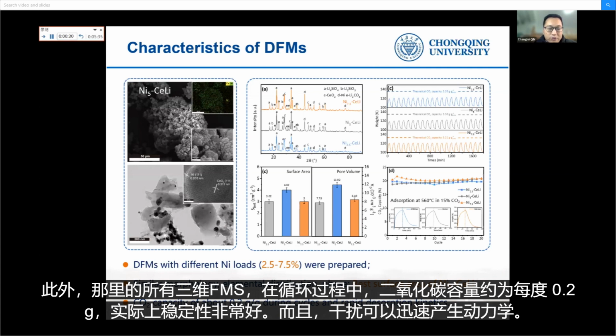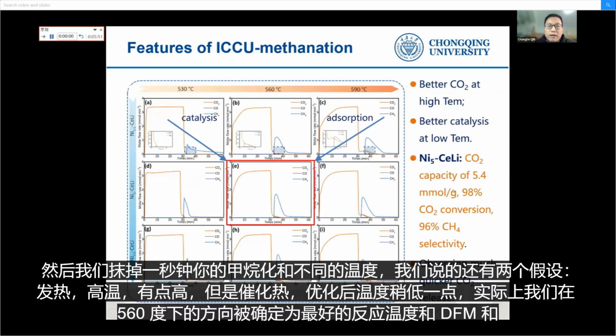Additionally, all these 3 DFMs have a CO2 capacity of about 0.2 gram per gram during the cycles, and the stability is very good. Also, the desorption kinetics is rapid. Then we tested the ICCU methanation at different temperatures.